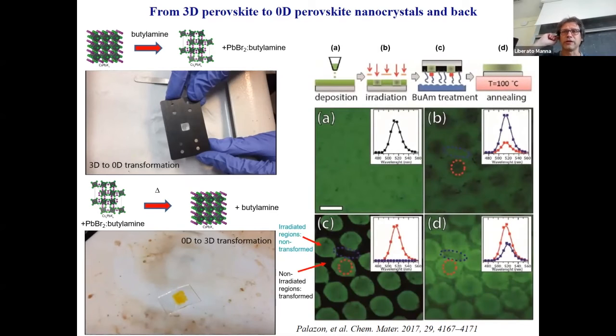You can do something more complicated. You can make a film of nanocrystals and irradiate with X-ray a certain region of the film, for example, as you see in panel B. The regions which have been irradiated by X-rays, marked with this red circle here, become refractory to these reactions because the ligands form a sort of protecting layer, since they have been cross-linked by this radiation damage. And so when you expose the film to the butylamine vapor, the irradiated regions are not transformed. They remain in the 3D perovskite because butylamine cannot enter it.